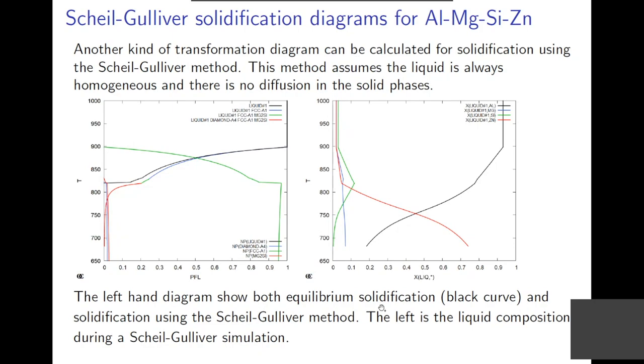But if you assume, according to Scheil-Gulliver, that there is no solid phase redistribution, so no diffusion in the solid phase, then the initially solidified aluminium will have much lower alloy content than the liquid, and the liquid is assumed to be homogeneous, so the total amount of liquid will follow this curve. And this is the total amount of aluminium in your system. So you get liquid stable down to 200 degrees lower than in equilibrium solidification. And this is the composition of the liquid during this Scheil-Gulliver simulation. And you can see that the final liquid, this is the fraction of zinc in the liquid phase. So you have almost 80% zinc in the last liquid formed here. So this is a segregation. You can simulate the segregation very well by this method.